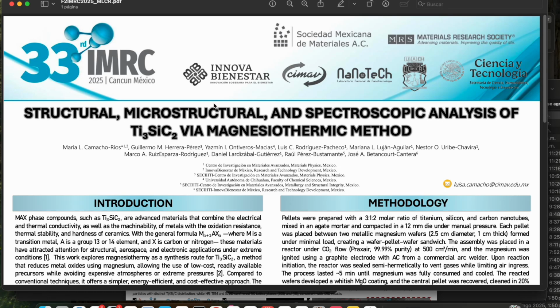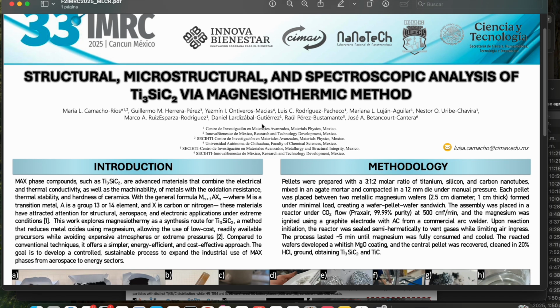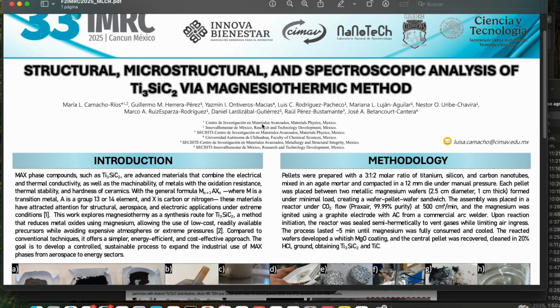This talk introduces a fast, low-cost magnesiothermic route to synthesize the MAX phase Ti3SiC2 and explains the structure-processing-microstructure links we validated. MAX phases combine metallic conductivity and machinability with ceramic-level thermal stability and oxidation resistance, which is why they keep showing up in high-temperature structural concepts.